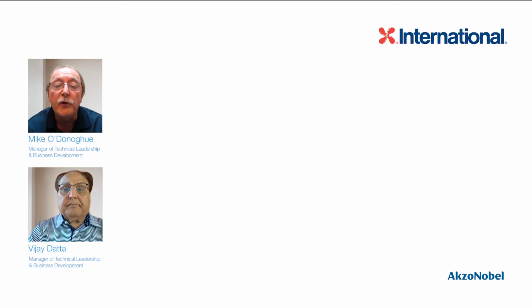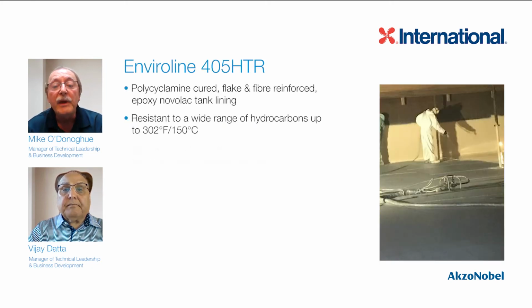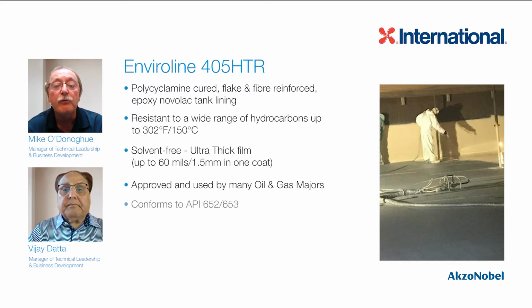In terms of the actual formulation, as you mentioned earlier, it's a polycyclamine cured epoxy, but we have in there a flake and fiber reinforcement. So it's actually a reinforced Novolac tank lining, and it's resistant, as we've said, to about 300-ish Fahrenheit, 150 centigrade, solvent-free, ultra-thick film, what we've talked about before, but key here, approved and used by many oil and gas owners, majors worldwide. And you're going to come to this, it conforms to API 652, 653.